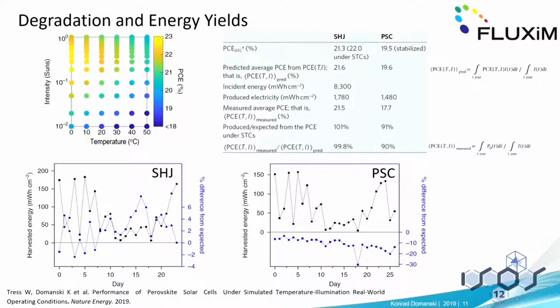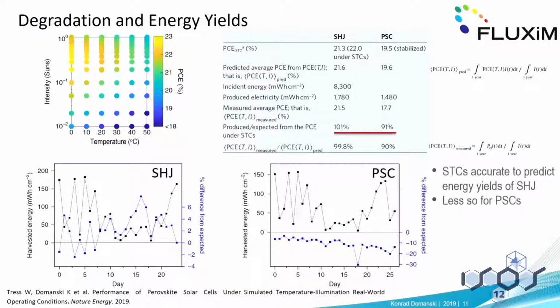So here I plotted a table. This is how efficient our devices were at the beginning. This is what we measured under standard test conditions, under 1 sun, 25 degrees. This is what everyone measures. This is what we predicted to be the average efficiency across the entire experiment, again, by using this data. So we see that it's a little bit higher for both cells. This is how much energy was incident on the devices, and this is how much energy they generated. And now the measured efficiency across the entire experiment was very close to the predicted one for silicon, and 2% lower for perovskite. And so we see that it's 100% of what we expected from standard test conditions for silicon, and only 91% for perovskite.